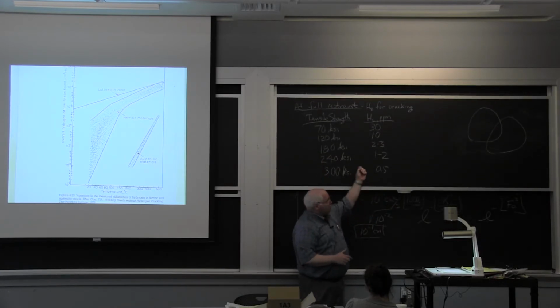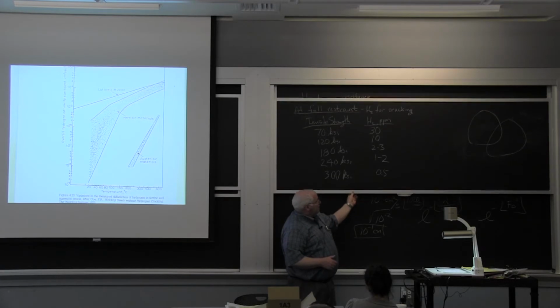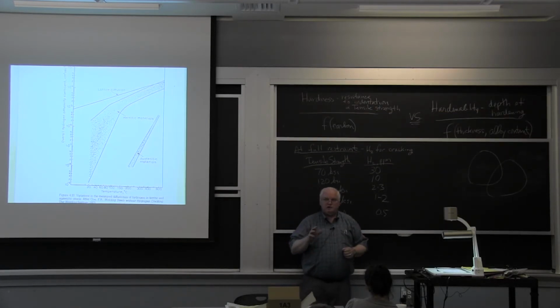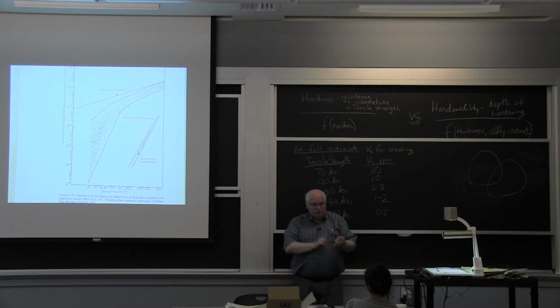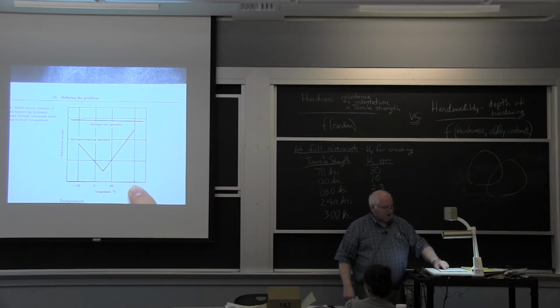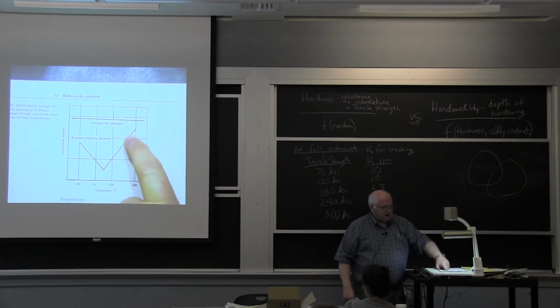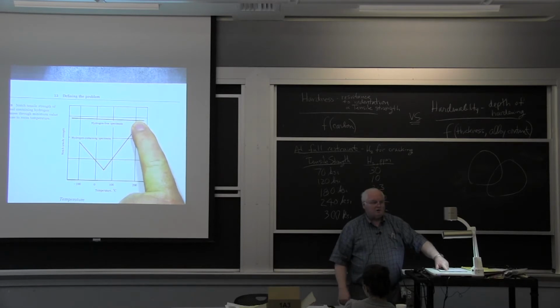If I have a higher strength part, the ASME standard, it's not a code, says you got to put it in within 1 to 4 hours, and you either heat treat it for 4 hours at 375 degrees Fahrenheit. Where did they get 375 degrees Fahrenheit? I don't know. Calculate it in centigrade and see if it came from Europe or the United States. But 375 sort of works as a high enough temperature from a plot like this. 375 is probably something like 200, and you're getting up here to almost as good as unnotched, okay?